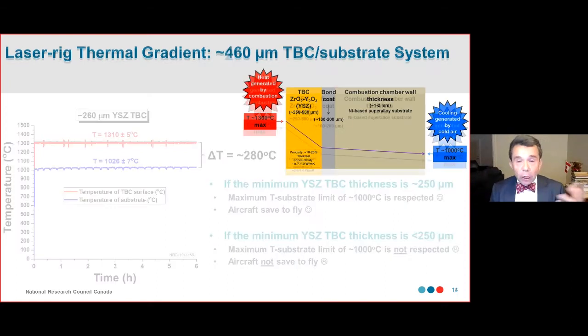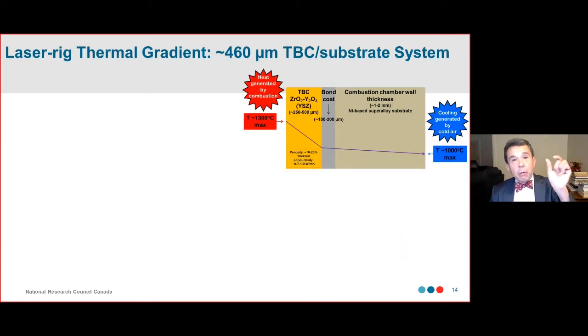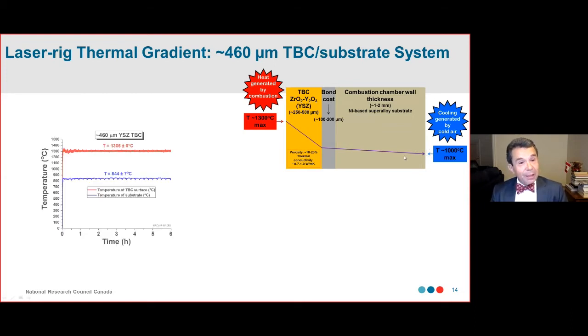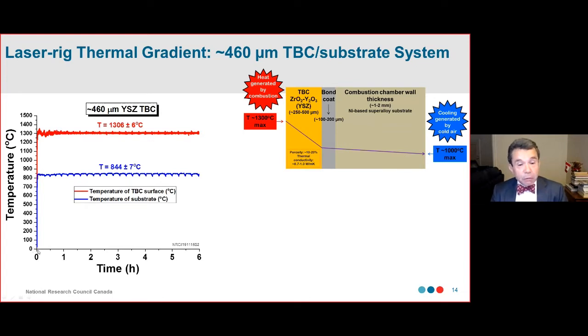Let's see what happens the other way. Here, for example, I'm going to put the other extreme, a 460 micron thick TBC. This temperature here should be around 1,300 degrees Celsius, and the temperature here cannot go over 1,000 degrees Celsius. Let's see how it works. You can see the graph. We performed the experiment for 6 hours, and we did it. The temperature over the surface of the TBC was about 1,300 degrees Celsius, right there, and the temperature of the substrate was about 844. So we have a gradient of 460 degrees Celsius.